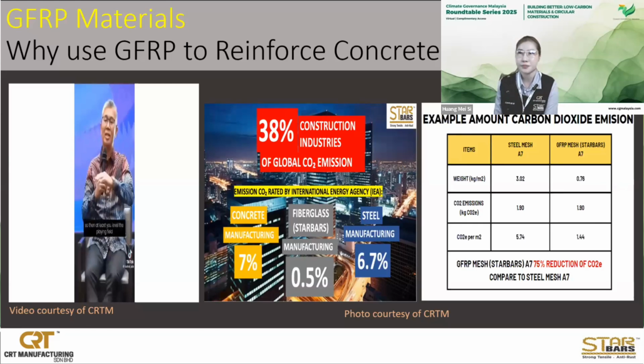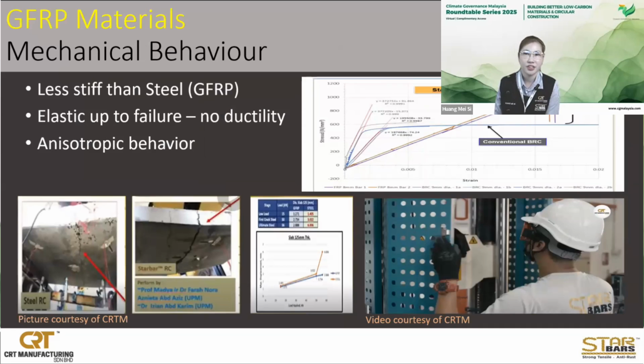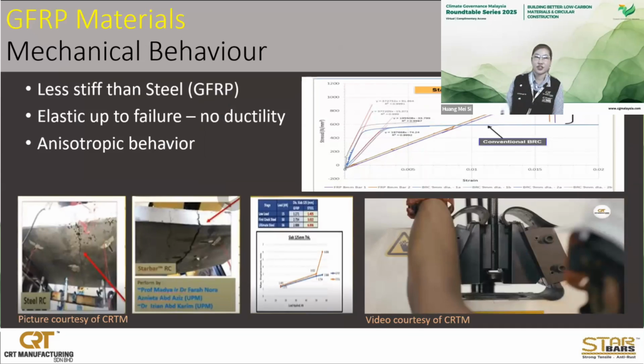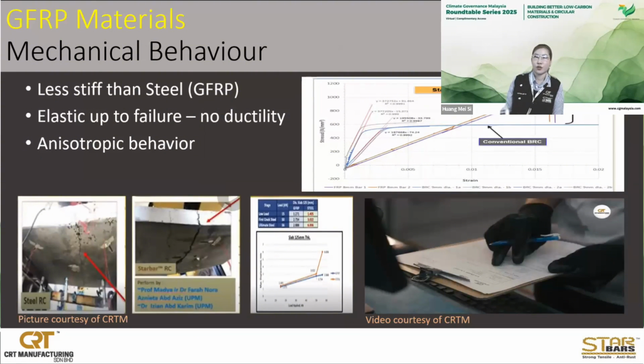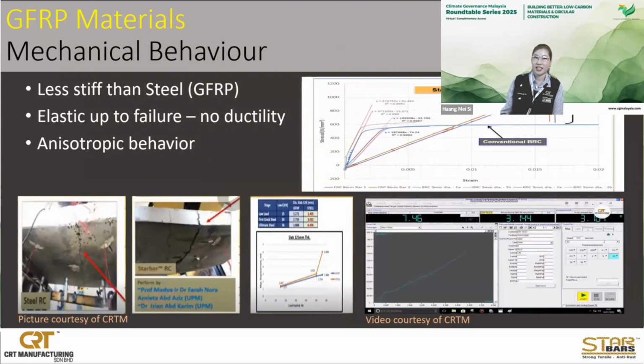Next. So this material, compared to steel, has lesser stiffness, low E values, is linear elastic up to failure with no ductility, and is anisotropic. So for engineers, if you look at the stress-strain curve on the right-hand side, the blue color is steel, which yields at 500, whereas the orange and purple lines are GFRP bars. The stress point is 2 to 3 times higher, whereas it is not ductile.